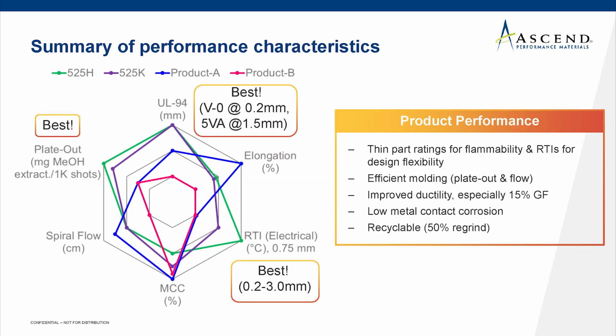And this is a summary showing how our product compares to the competing products A and B. This is a spider diagram, and the best performance are values that are on the outside of the spider diagram, whether they're high or low numbers. We reflect that as being better on the outside of the diagram. And this is showing that we achieve thin part ratings for flammability and RTIs for better design flexibility. We could get V0 down to 0.2 millimeters, as well as 5VA at 1.5 millimeters. And our RTI electrical actually spans 0.2 to 3, which is very broad compared to most of the competitor materials.